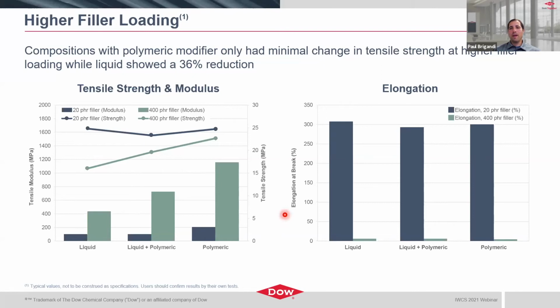Nothing, I would say, dramatically evident from the elongation, as expected. We can see that the polymeric material does not impact the elongation properties and it's maintained. Obviously, with 400 parts filler, you would expect your elongation to decrease significantly, which is what we see. But again, no real significant difference between the combination. And you can see when you blend or mix the two, you end up about in the middle.